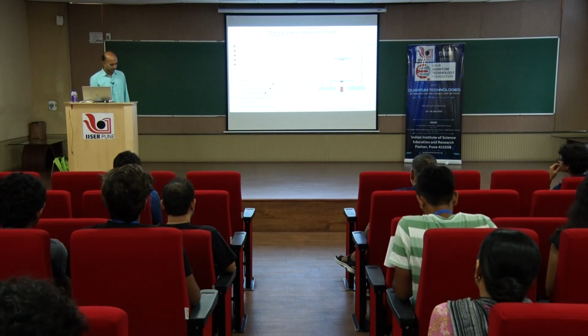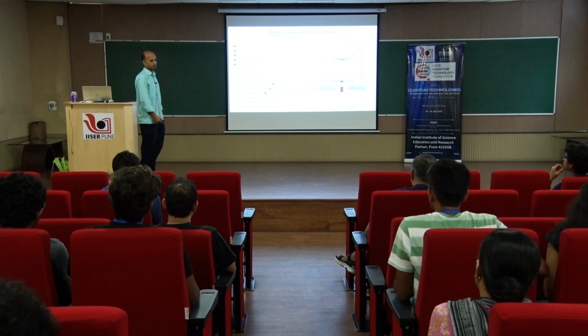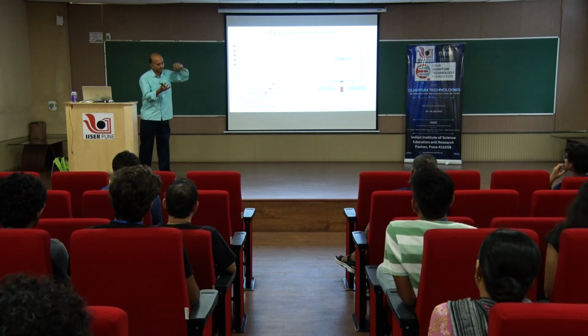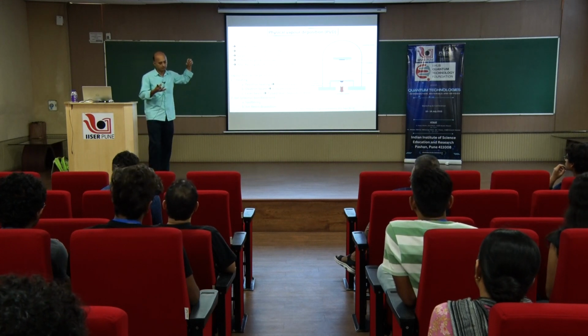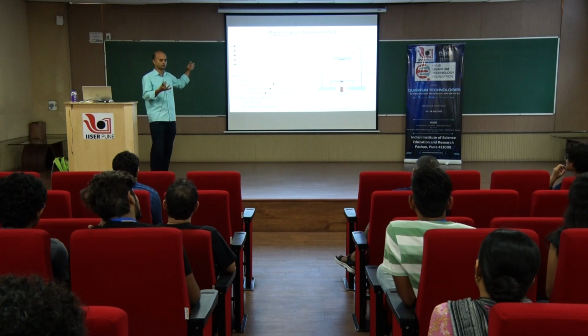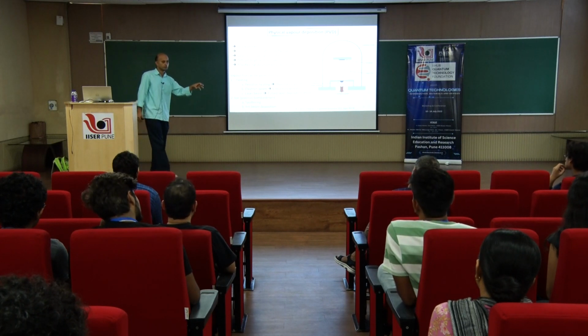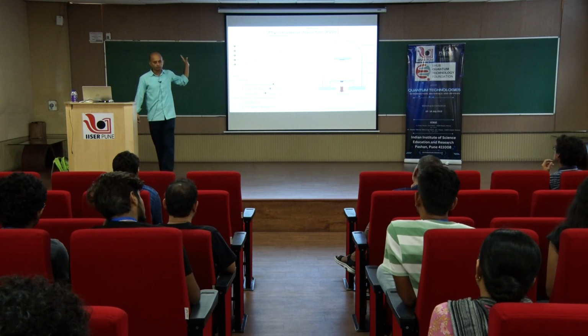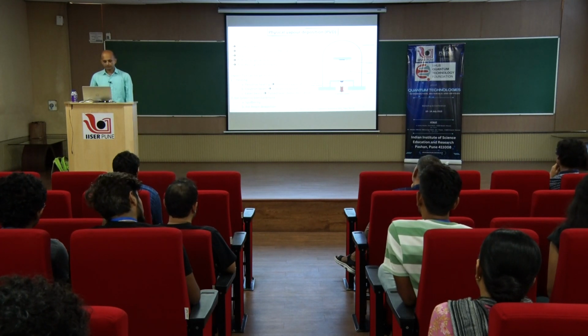What is sputtering? Sputtering is a machine where you make a plasma, mostly argon plasma, and then you guide it to a material which you want to deposit. That high energetic plasma, or the ions, will come and hit that material, and physically remove that material. Basically, if you are close to a mud puddle and throw some stone on it, you splash some mud. So, it works almost in the same way.